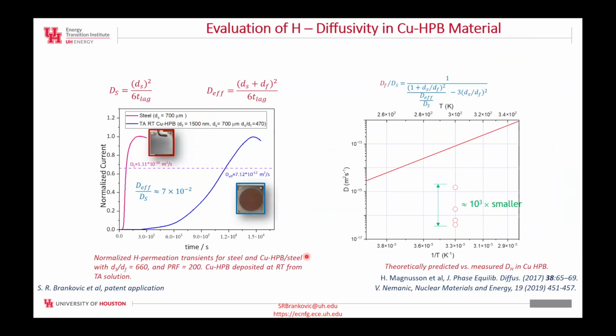So then we can do more analysis of these permeation transients, and we can extract the diffusivity of hydrogen through steel, through effective diffusivity to copper-coated steel. We can do some scientific evaluation. One of the things that I want to show you is that when we calculate the diffusivity of hydrogen in a copper that we electrodeposit or actually deposit on the steel versus the copper that is in the literature data, we are actually about 1,000 times smaller.